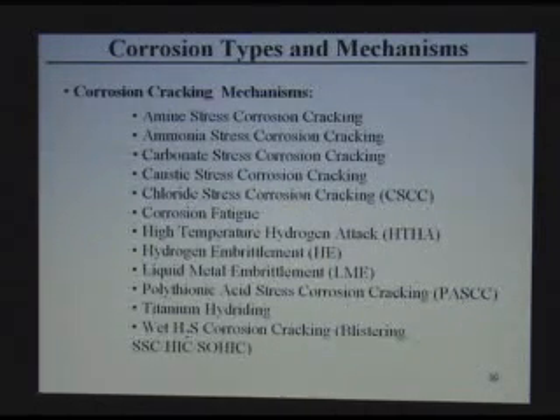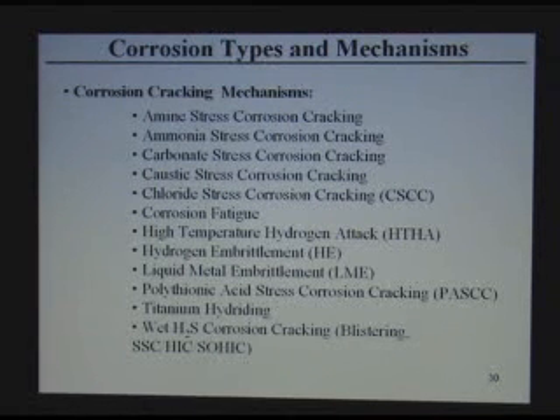Types of corrosion: cracking. The ones I mentioned before were mostly corrosion metal loss type. But here we're talking about cracking. As I mentioned before, we have stress corrosion cracking, which happens for carbon steel at certain temperature if you don't have stress relief. Ammonia also creates stress corrosion cracking for copper alloys. So we never use copper alloy if a stream has ammonia in it. We cannot use it, otherwise it will crack.